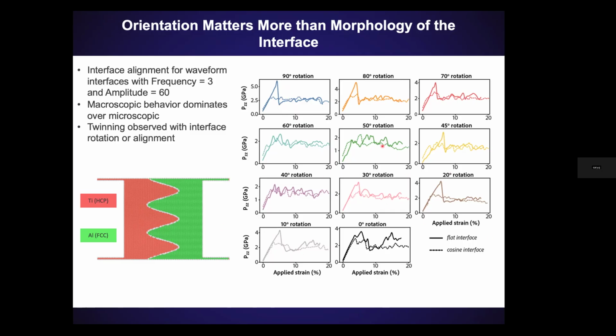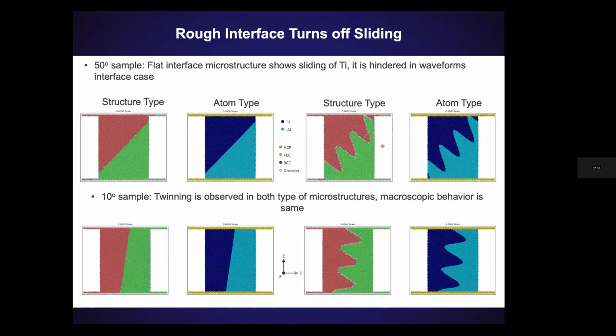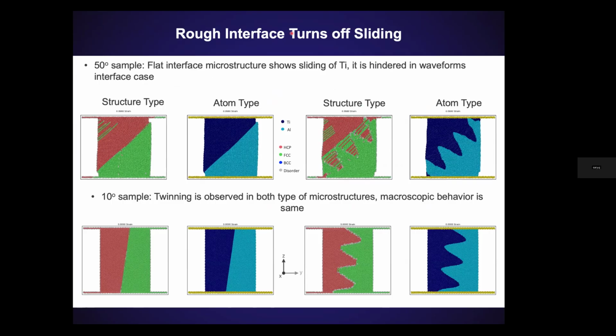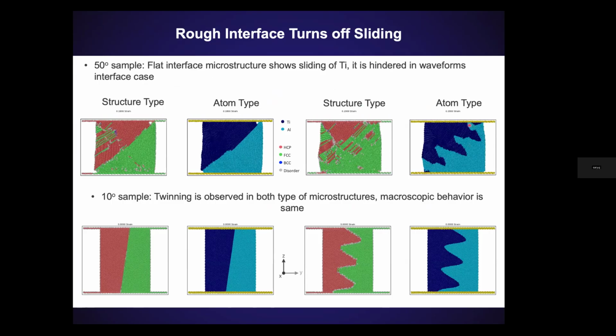What that told us is that the orientation of the interface with respect to the loading condition will matter more than the exact shape at the interface. What does that mean in practical terms? Maybe that little detail at the interface, if you diffusion bonded it or additively manufactured it, is not going to matter as much for practical applications, at least under uniaxial stress loading. Well, what about shock? We're going to talk about that. Here, I'm just showing movies where, when you have a flat interface, you get sliding between the materials, whereas when you have these perturbations, they lock the materials together and prevent that sliding.